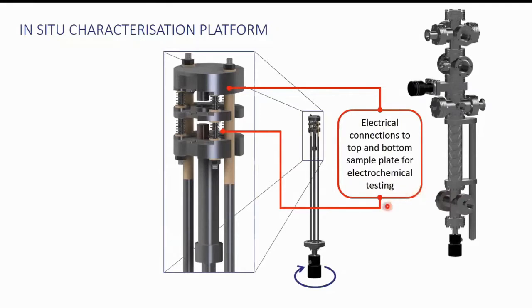our clamped battery components. Before transfer, the components will be unsandwiched, if that's a word, and rinsed if necessary to remove electrolyte. After characterization, they'll be transferred back into the in-situ chamber, reassembled with the electrolyte reapplied, and cycled further, continuing the process without breaking atmosphere.